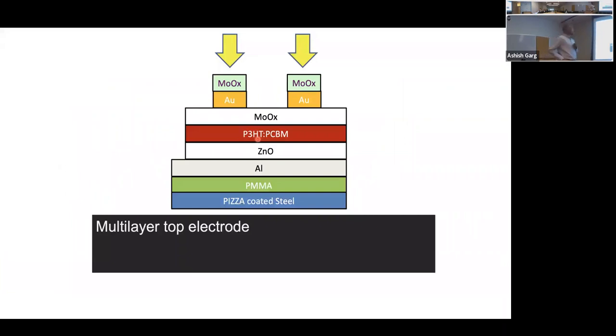This is where we stumbled upon the idea of having multi-layer electrodes on top. If you dig into the literature, you see that if you make metal dielectric stacks, by tuning the refractive index and the extinction coefficient, you can increase the transmission of the top electrode by making a multi-layer electrode rather than just a single layer electrode.